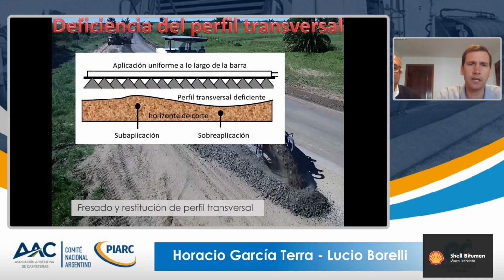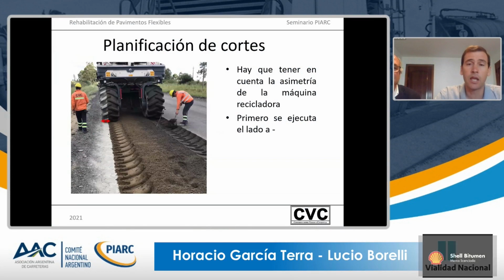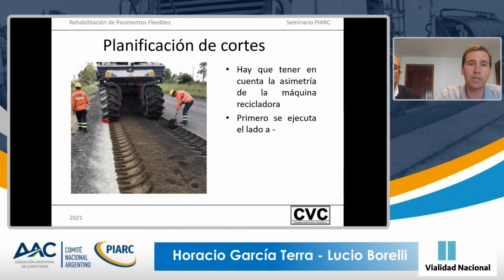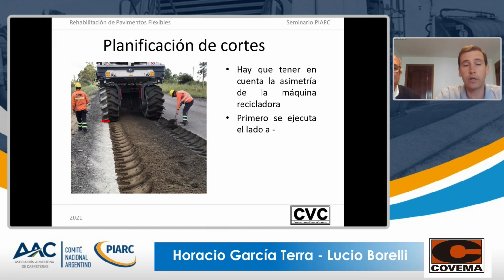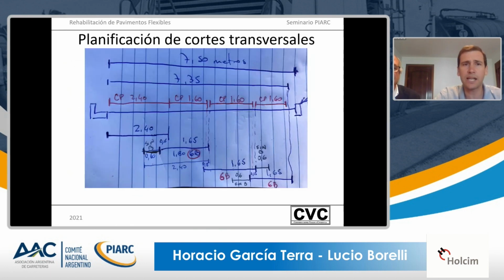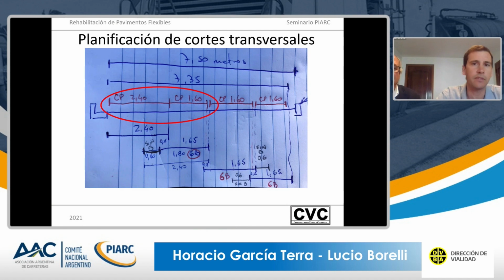Pre-profiling is very important because if there's a deficiency when you apply this foam asphalt together with the Portland cement, maybe there will be under or over application of these materials. The cut planning is one of the most important tasks when you are going to recycle a road. But you need to take into account the asymmetry of the recycling machine, because the right side recycles next to the roads and on the other there's a half a meter mismatch. I don't want to enter into too many details about the planning of the cross-sectional cuts, but it depends on